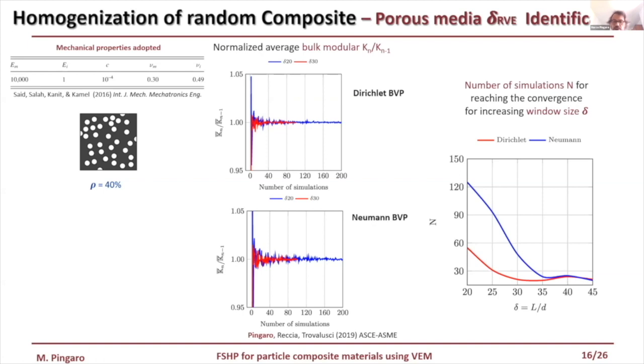In this slide is reported the minimum number of simulations required for reaching the convergence at varying the window dimension. In red line, the Dirichlet boundary condition, and blue line, the Neumann boundary condition. The two bounds tend to decrease, and they tend to the same value when the window dimension is increased. Is good.